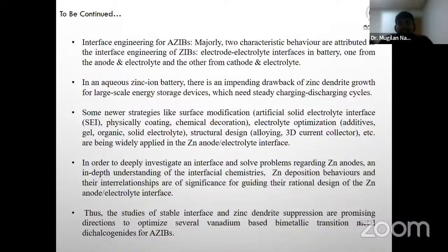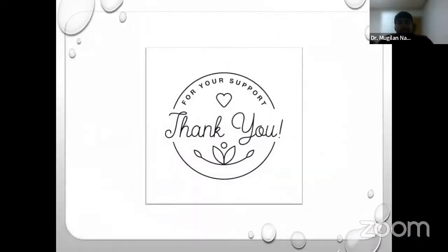Some newer strategies, like surface modification, artificial solid electrolyte interface, physical coating or chemical decoration, electrolyte optimization with additive gel or organic solid electrolytes, and alloying the material with another material, are widely applied at the zinc anode electrolyte interface, in order to deeply investigate the interface and solve the problems regarding the zinc anode, and to understand the interfacial chemistry like zinc deposition behavior. Some electrodeposition on the top layer of the zinc sheet can also be done to improve the rational design of the anode electrolyte interface. Thus, studies of stable interfaces and zinc dendrite suppression are a promising direction to optimize several vanadium-based bimetallic transition metal dichalcogenides. That's all about my presentation.